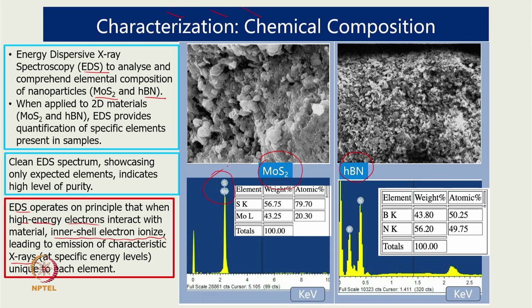In the case of MoS2, we are getting those two peaks. Sulfur is around 79.7% atomic percentage and molybdenum is around 20.3%, while the weight percentage is 56.75. So this shows that the purity level is good. Coming to hBN, again here N and B, and we are able to see that B is around 50% atomic percentage, and N is 50%. Coming to weight percentage, here it is 43.8% and 56.2%, and the x-axis is the electron volt energy, and every material has a different kind of result. Here we are able to see that this value is much lesser compared to this value.